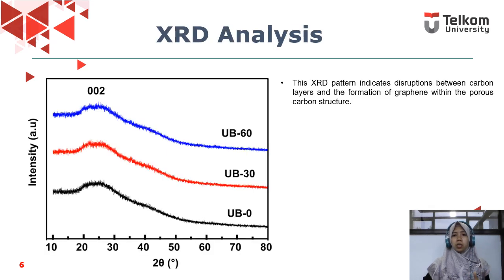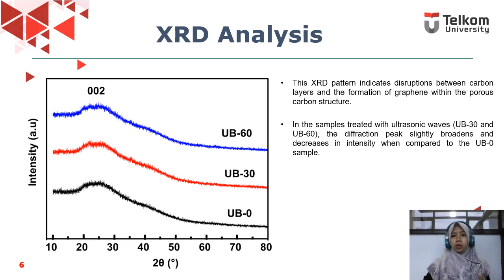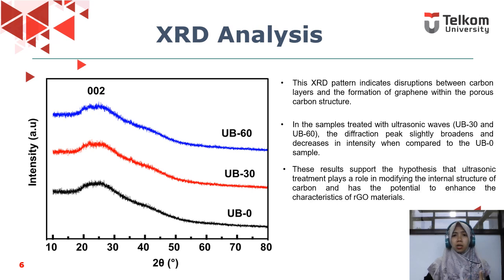Here is the result and discussion. XRD analysis. This XRD pattern indicates a disruption between carbon layers and the formation of graphene within the porous carbon structure. In the samples treated with ultrasonic wave, UB30 and UB60, the diffraction peak slightly broadens and decreases in intensity when compared to the UB0 sample. This supports the hypothesis that ultrasonic treatment plays a role in modifying the internal structure of carbon and has the potential to enhance characteristics of RGO materials.